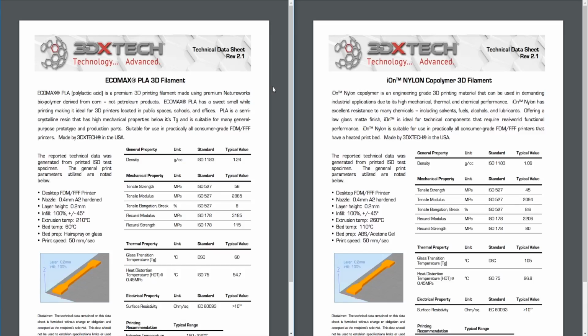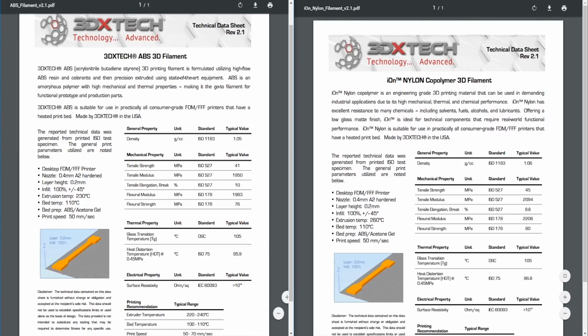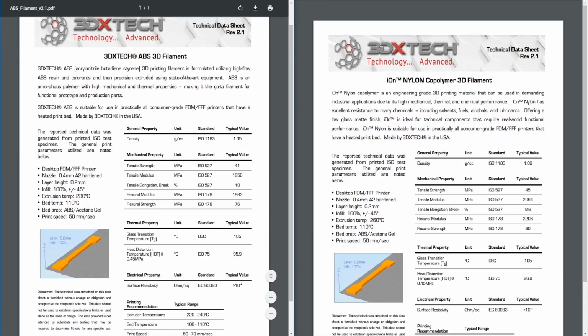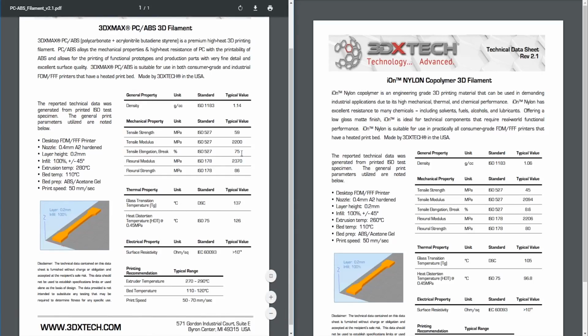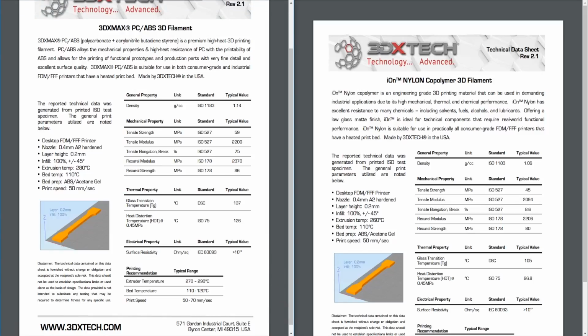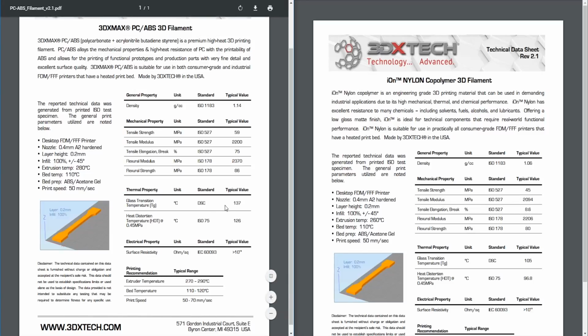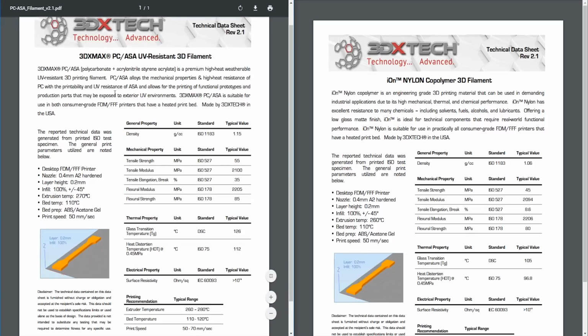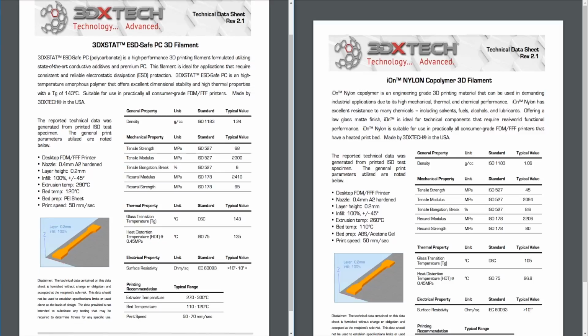In the first part, we went through the EcoMax PLA as normal against ABS versus the rest of them, so the standard ones that you're used to versus everything else. Then we looked at polycarbonate ABS, which was our surprise powerhouse as far as toughness, strength, stiffness and temperature stability. Then we had the polycarbonate ASA UV resistant, which was basically similar to the polycarbonate ABS, except you would use it for UV resistant material so that it would be sitting outside and not degrade the strength of the plastic.